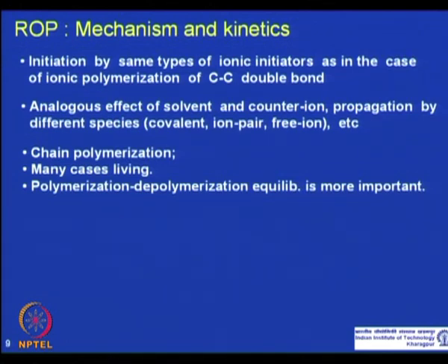If you take care of your reaction medium so that there are no impurities, then these polymers are living, so you can make block copolymers or functional polymers at the end of the reaction. And in this case, unlike the linear polymerization of vinyl molecules, the polymerization depolymerization equilibrium is very important.